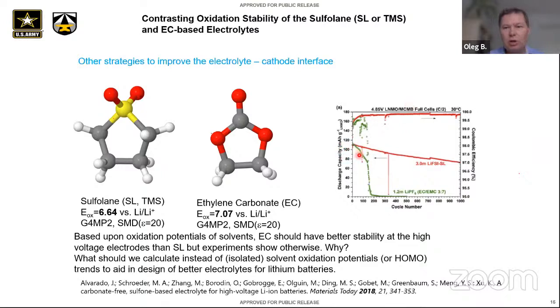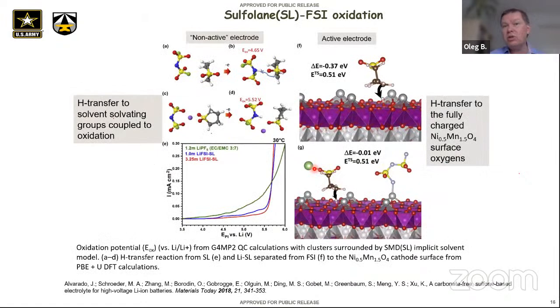Actually, our collaborators, Judy and Marshall Schroeder, observed that it decays pretty fast for a traditional carbonate electrolyte, but in a 3 molar lithium FSI sulfolane electrolyte, the discharge capacity keeps on going. That could indicate an initially interesting decomposition mechanism, but it's clearly not the oxidation stability correlation. So there should be something else. To understand what that something else could be, we looked more at our methodology for screening non-active electrodes, because there are carbon particles all over, and there could be oxidation occurring on them.